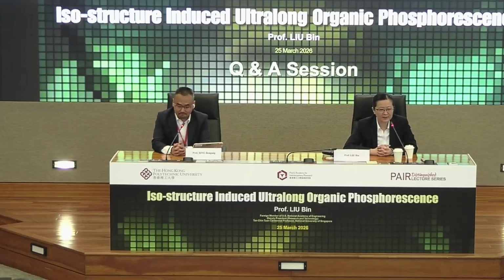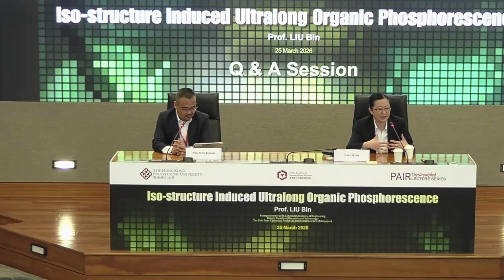Okay, that's a great question. A very broad question that cuts across two disciplines within the broad context of organic fluorescent materials. I have been working on AIE, which stands for aggregation-induced emission, for many, many years, and I'm still working on that. That one is a phenomenon. The phenomenon shows that when molecules are very well dispersed in the solvent media, they have the freedom to rotate and interact, so that this molecular motion or other mechanisms may dissipate the energy. As a consequence, you don't see a strong background signal when the molecules are very well dispersed. But once you induce aggregation, you can form nanoparticles, you can form aggregates, you can do spin coating into films.